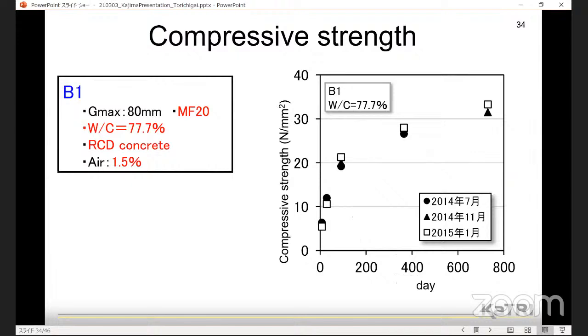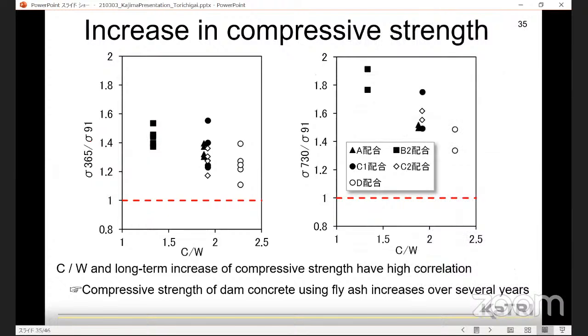And this slide shows the compressive strength development of B1 RCD concrete. That's similar to slump concrete. So compressive strength increases after 91 days, and then I try to show the relationship between the cement water ratio and the increase in compressive strength for about 1 year and 2 years compared to the 91 days compressive strength.